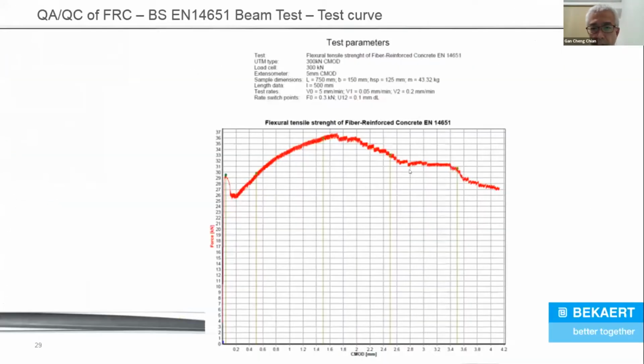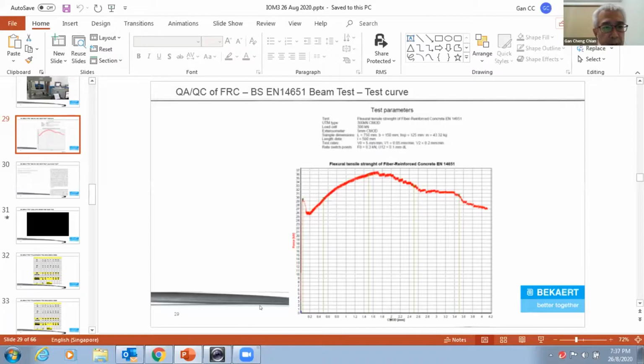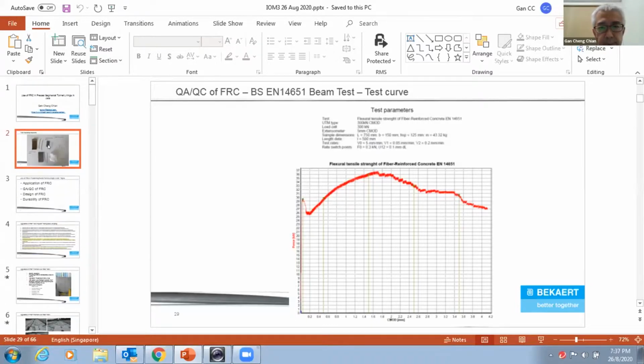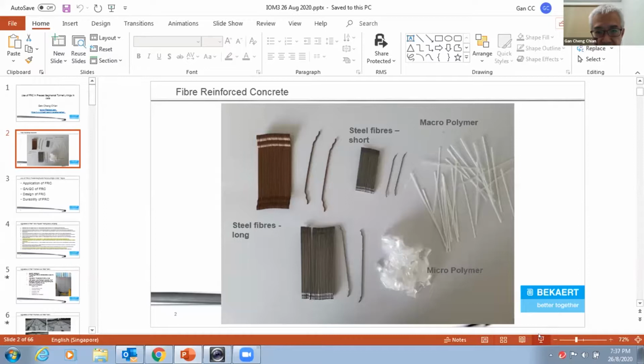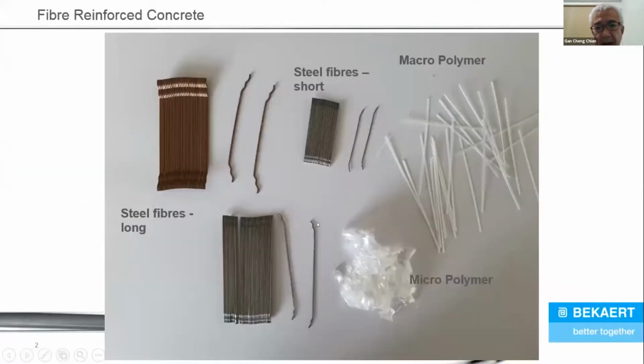Okay, so if the concrete compressive strength is too high, this back end will drop too low. And when it drops, it's purely because the fiber itself is breaking up. So fiber breaking, what does it mean? That means these fibers here, the hooks here, are actually breaking. So when the hooks are breaking, it will release the strength. So that's not good. So what happens is that you need a higher strength for the steel fibers.